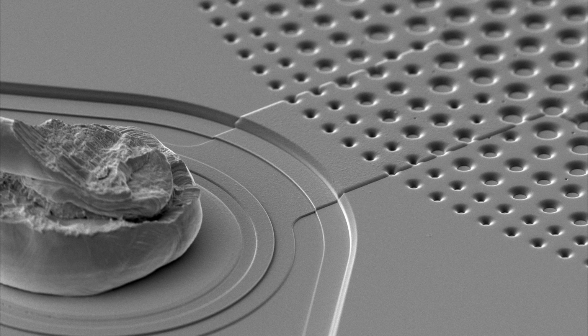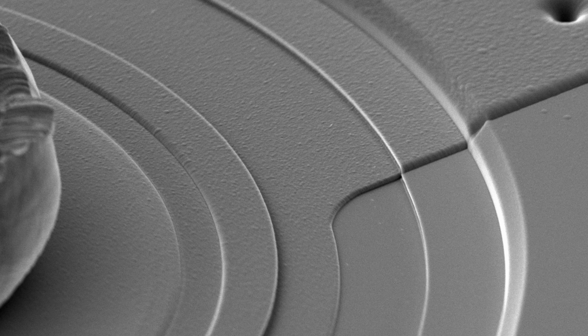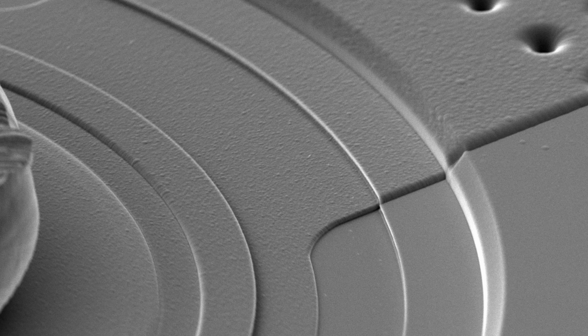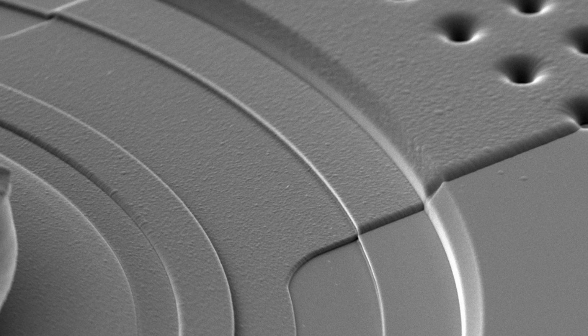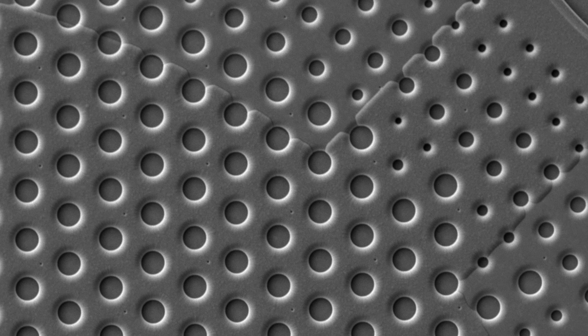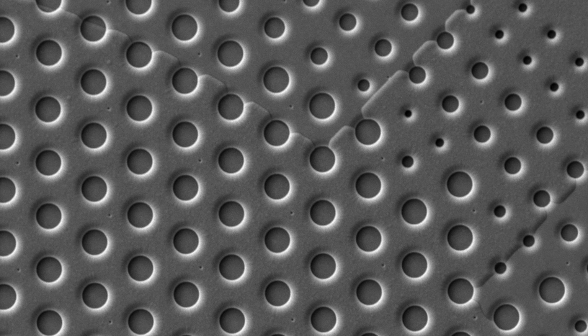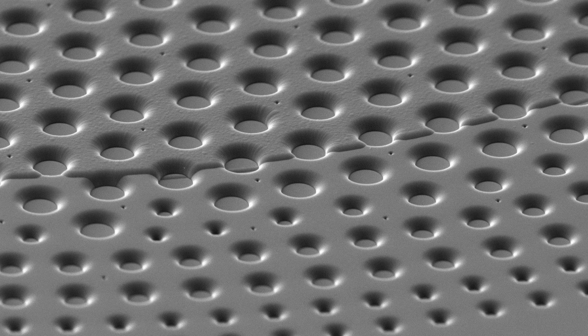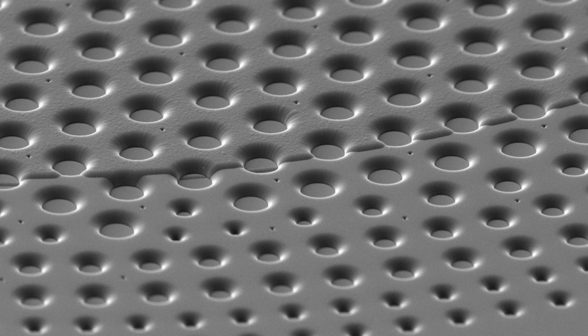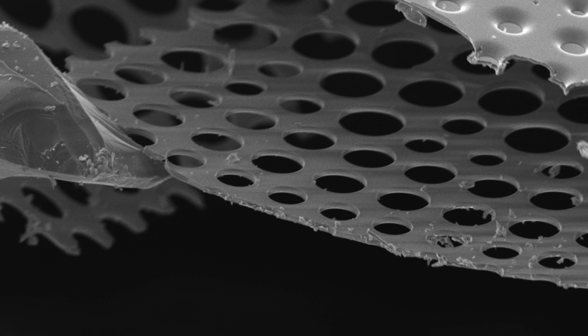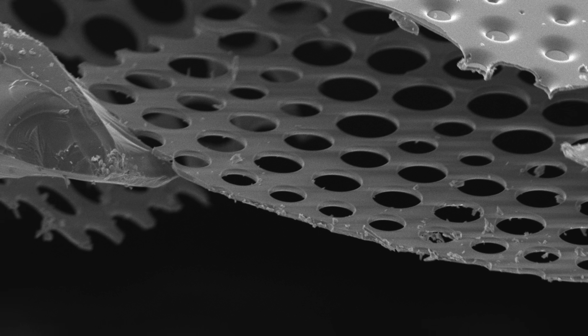In contrast, the top layer is connected by this kind of rounded layer on top. This is probably a highly doped polysilicon layer. Polysilicon is just another form of silicon that can be deposited during later processing steps, but it has a more characteristic rounded profile, instead of the nice crisp clean lines like we see on the lower layers. And underneath it all is that deep cavity.